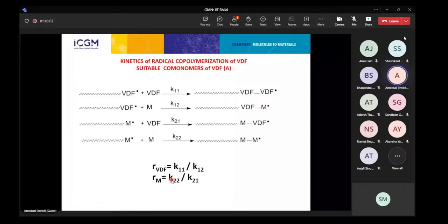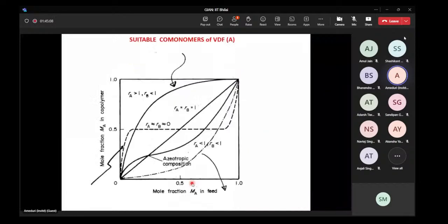And indeed, when I look at the literature, if you consider the diagram of composition, which means the mole fraction of monomer A, for instance VDF, in the copolymer versus the mole fraction of monomer A in the feed that you put in the autoclave, if you are 50-50 in the autoclave, the copolymer doesn't necessarily have 50-50 because you have a different reactivity of both comonomers. So for instance, if you take some HFP, hexafluoropropylene, this kind of monomer, or perfluoroalkyl vinyl ether, which are not homopolymerizable, you are going to get this kind of behavior.